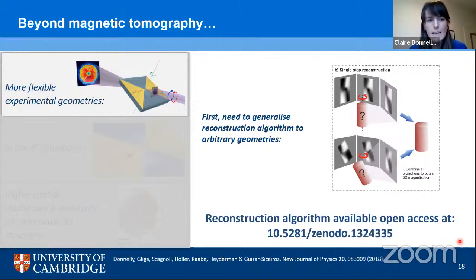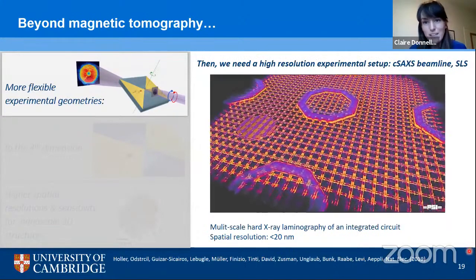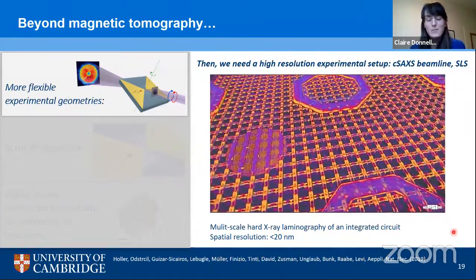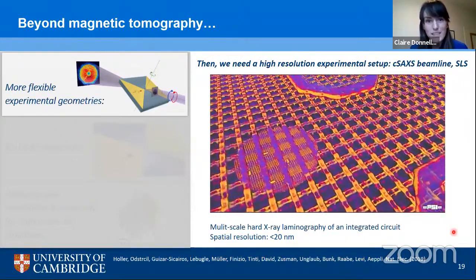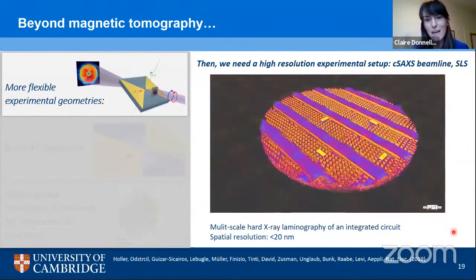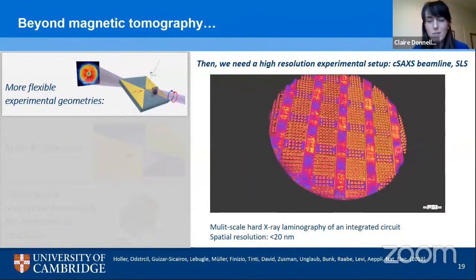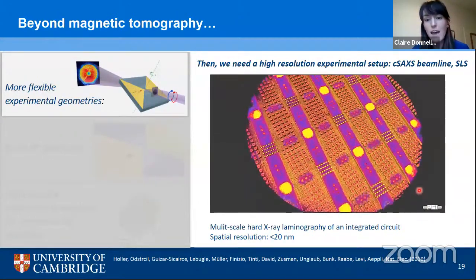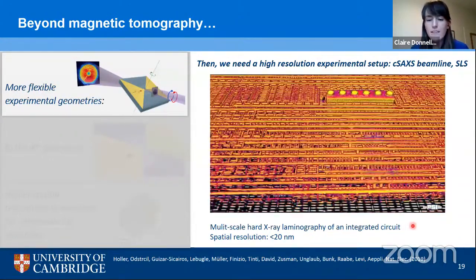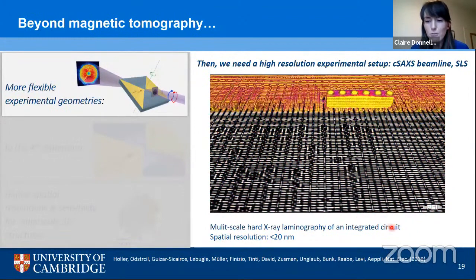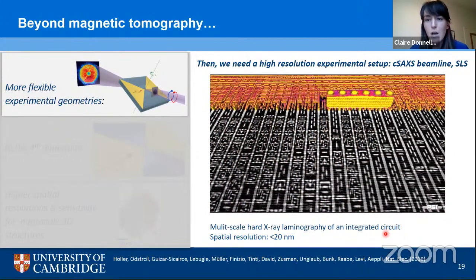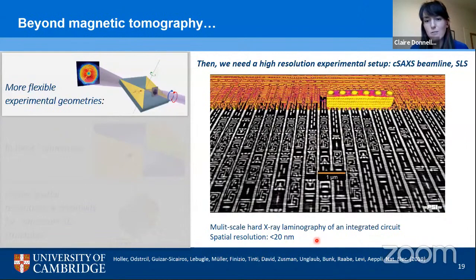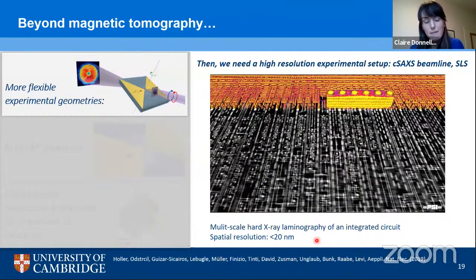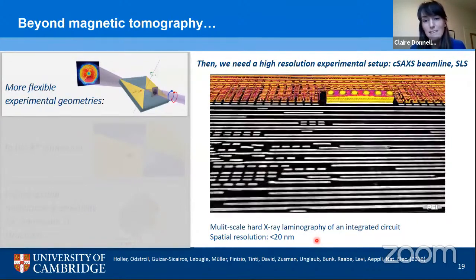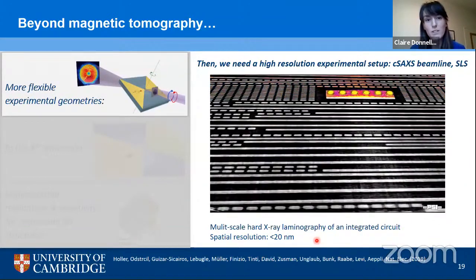Secondly, we needed a high resolution experimental setup. And for that, we went to the cSAXS beam line at the Swiss Light Source, where they were developing a high-resolution laminography setup. And what I'm showing you here is a first demonstration of non-magnetic laminography at their beam line, where you can see they're measuring the nanostructure of an integrated circuit with very, very high spatial resolution. Now, this high stability and high resolution setup was perfect to allow us to go on to do our first